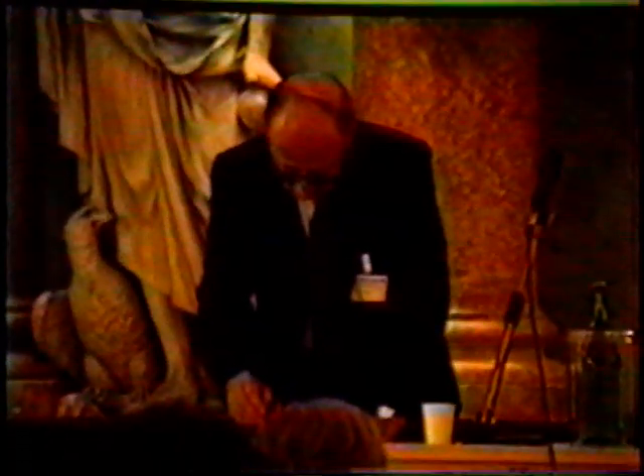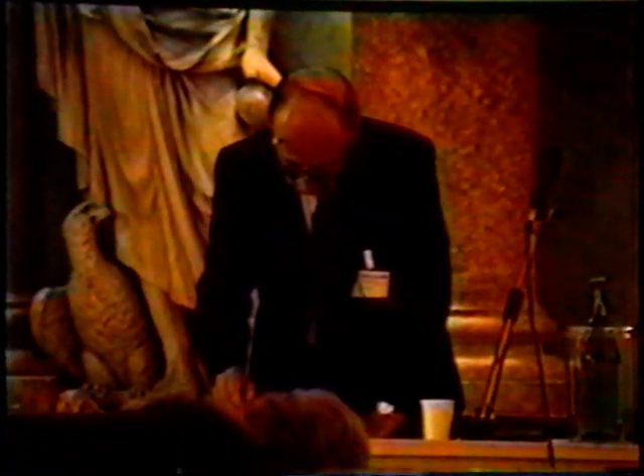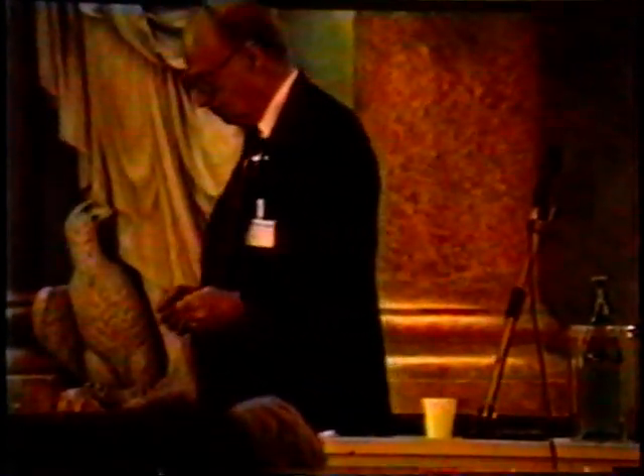Secondly, your comment on the impurities. Yes, if we avoid the dissolution of the anode, that's the first important step to be taken. But it's only part of the way, because both of us know very well the standard techniques in electrochemistry that have to be applied in order to clean up the electrolyte itself. And the standard techniques, for those in the audience that are interested in this, are the following, namely redistillation, filtering. In fact, one has to start with filtering first because there are ion particles in the solution. Secondly, followed by redistillation in quartz. And thirdly, what we call pre-electrolysis, where one subjects the solutions to many hours of pre-electrolysis to clean out the ionic impurities.